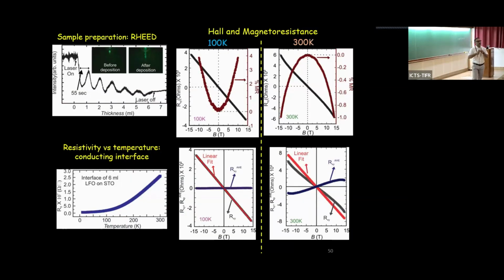RHEED oscillation means you are looking at how the sample is growing and how many monolayers you are growing on top of your film. We have grown around 6 monolayers of lanthanum iron oxide on strontium titanate. The interface is completely conducting, going down to around 2K. Now, this is the interesting point.